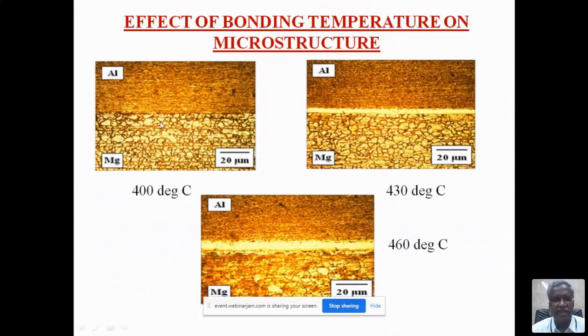So here we did a lot of experiments. We varied the temperature: 400, 430, 460 degrees centigrade. You can see the difference. When you use 400 degrees centigrade, the aluminum and magnesium sheets are bonded, but at the interface there is no interlayer, no diffusion layer. But here you can see the diffusion layer, the white colored layer. It's called the diffusion layer.